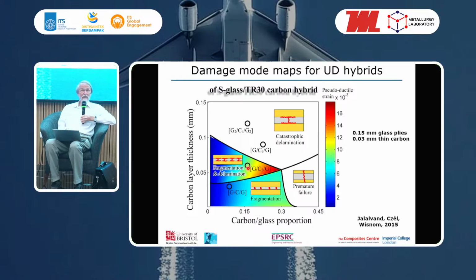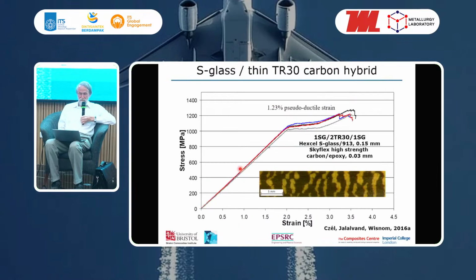So this particular one here is really quite interesting, because we can see from this prediction that we get more pseudoductile strain, and we're some way from this barrier, so we expect to see a pseudoductile response at that point. And that's exactly what we found when we did these tests. So this shows the stress strain response of this case, where we have S-glass and then 2 thin TR30 standard modulus carbon plies between S-glass. You see we have a linear response, then we get this fragmentation, we get this plateau on the stress strain response, we get progressive fragmentation along here, and then when that becomes saturated, we see an increase in the strain again.